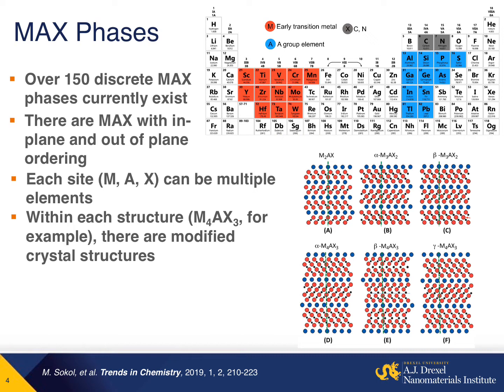Currently, over 150 different discrete MAX phases exist, and the full list of possible chemistries that occur in MAX phases is shown in this periodic table here. With these different MAX phases, you can actually incorporate multiple M elements, multiple A elements, or multiple X elements, or any combination thereof to create new solid solution MAX phases. Furthermore, with each different MAX phase structure, so M2AX, M3AX2, or M4AX3, or later as I'll show M5AX4, there's different structures that can occur. And this means there's different places where the M and X atoms can sit relative to A, or different orders where the M and X elements sit relative to each other.